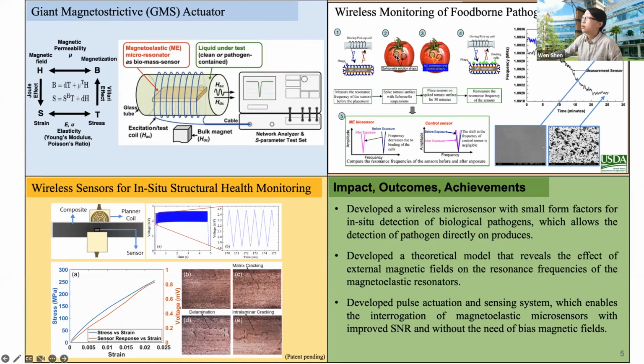And then these sensors, when we place them on top of the target, so here we use the tomato as an example, we spiked some salmonella contamination on these tomatoes, and if we place these micro-sized sensors on top of the tomato surface, they can pick up the target pathogen, which is salmonella here. The increase in weight from the target pathogen will cause the resonant frequency of this sensor to decrease. So we can measure in real time the decrease of resonant frequency caused by the detection of the target pathogen.